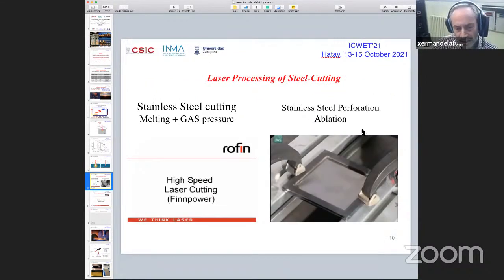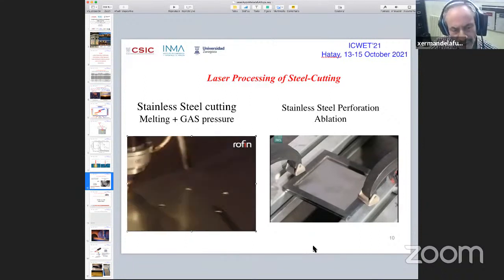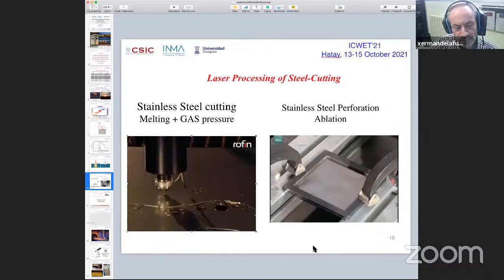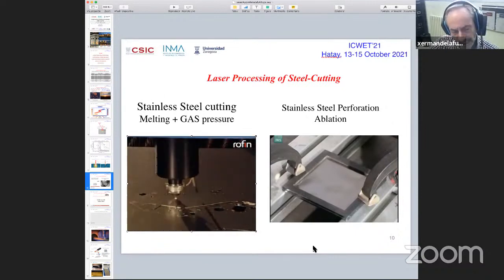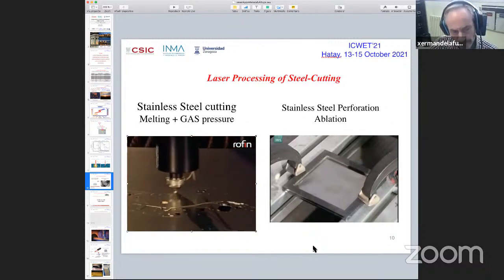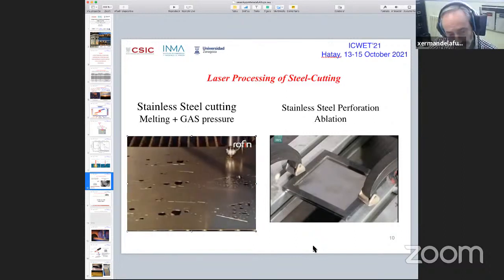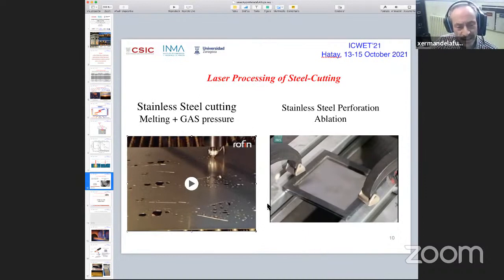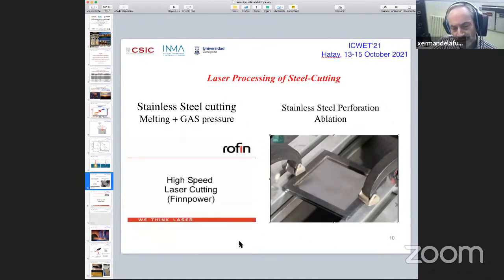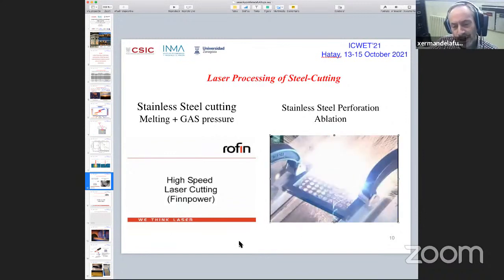So you can see two examples. You can see here a traditional metal cutting operation with the laser. It needs very high pressure gas to assist in removing the metal. Otherwise, the metal will be self-welded and you will not get a cut. As you can see, that's a very fast cut, but it's only by melting and gas pressure expulsion of this melt. This is a traditional cutting, but you can observe here on the right a video of a non-traditional cutting where ablation is also induced.